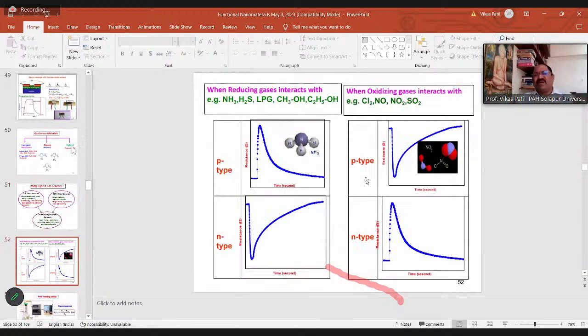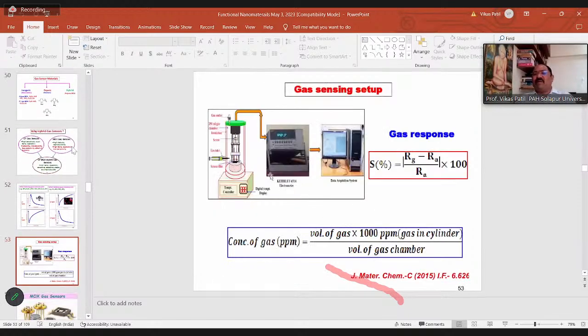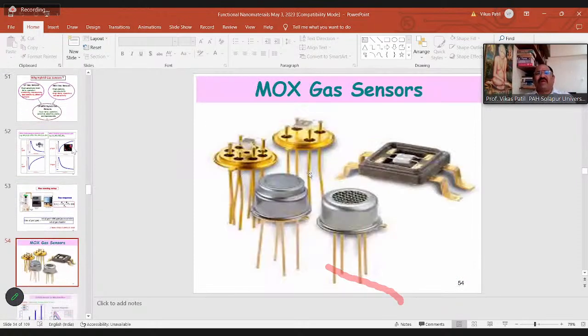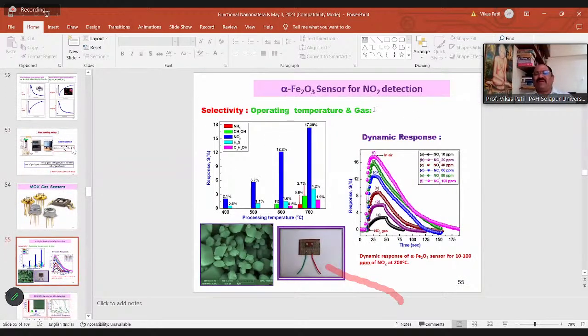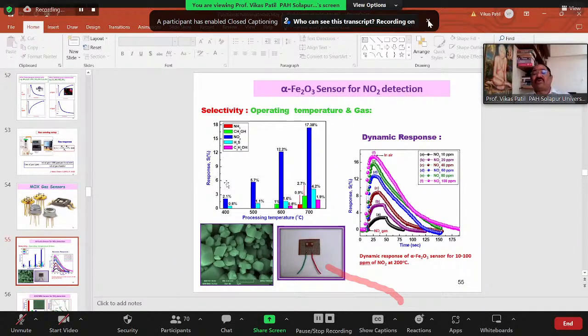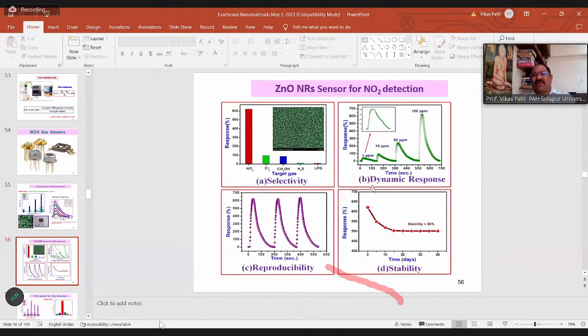These are the gas sensing mechanisms when oxidizing and reducing gases interact with P-type and N-type materials. This is the gas sensing setup we have used to measure resistance versus time. Now these are the sensors we have developed. This is an iron oxide sensor that detects NO2 gas. See that the linearity is very good. It shows response to 10 to 100 ppm of NO2 gas at 200 degrees Celsius, because metal oxide sensors are insulating and do not operate at room temperature. These are nano sensors.